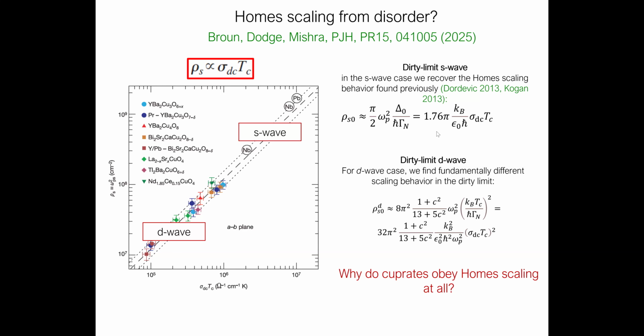the scaling, the Homes scaling, comes out of a very simple picture of a dirty s-wave superconductor. But if you do the same calculation for dirty d-wave, close to where TC goes to zero, in other words, you find that the scaling is different. It should go like TC squared, not TC. So, open question. There are many explanations out there, but why do cuprates obey Homes scaling at all, since we think that they're d-wave, and in some cases they are dirty?